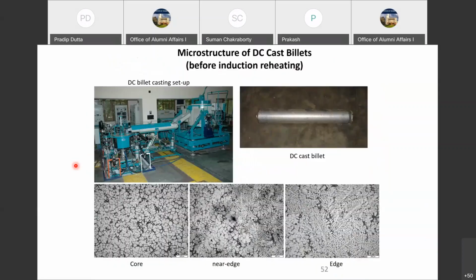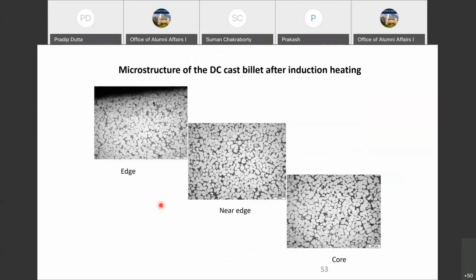So then we produce these DC cast billets, which had this microstructure. This is at the core, this is near the edge, and this is the edge. So across most of the billet cross section, we have this non-dendritic microstructure. But very close to the surface, solidification is much faster, so we can produce some dendritic microstructure there. That is what the induction reheating does to some extent.